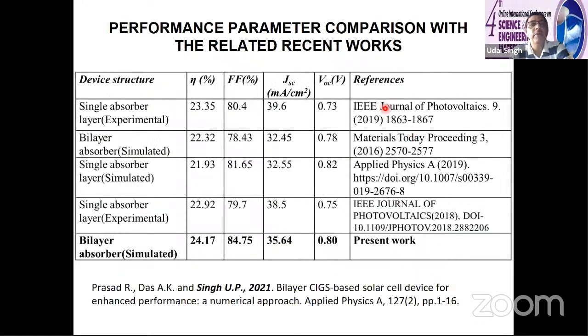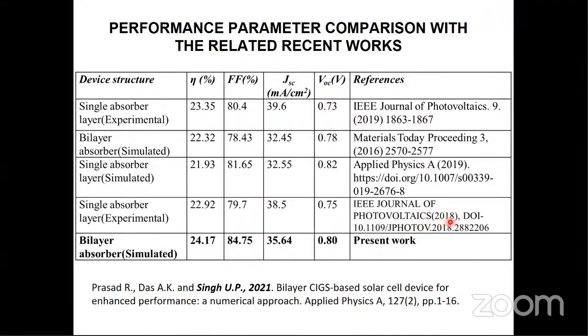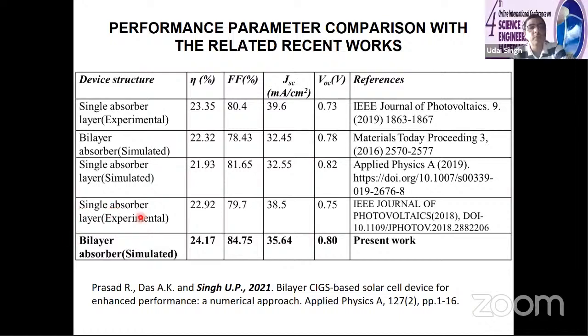We have also compared with different results. Some experimental single absorber layer has given 23.35, which is the highest. There are certain simulated results also, like bilayer and single layer, which have given 22.20 or 23. Recently, in 2018, a single layer experimental gave around 23%. So this is our present work which has given around 24.17, recently published in Applied Physics.